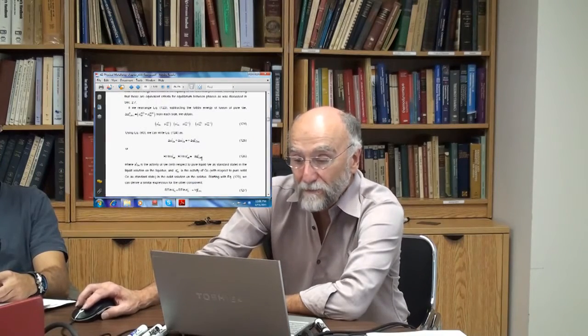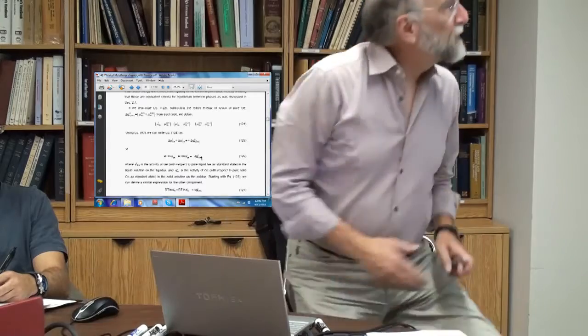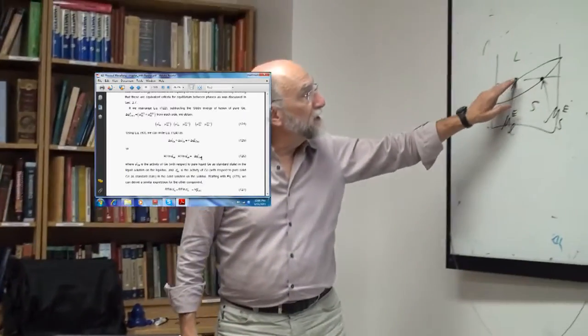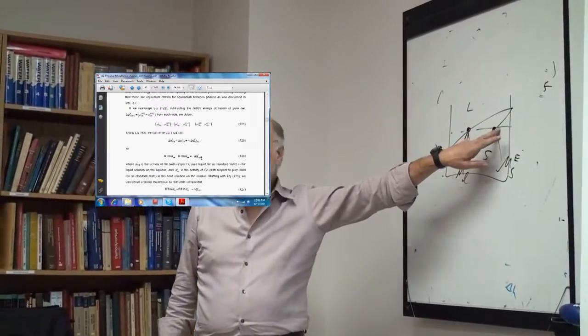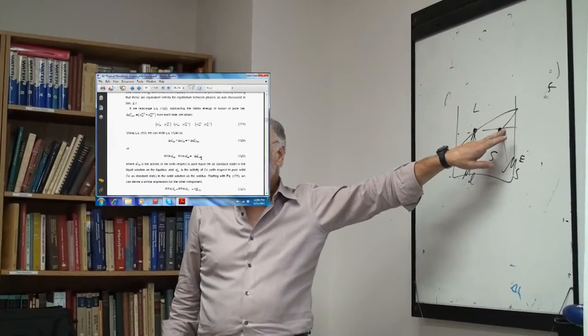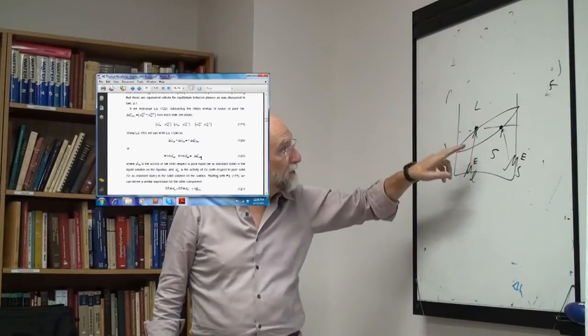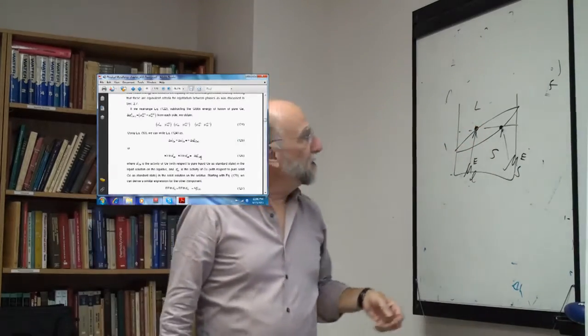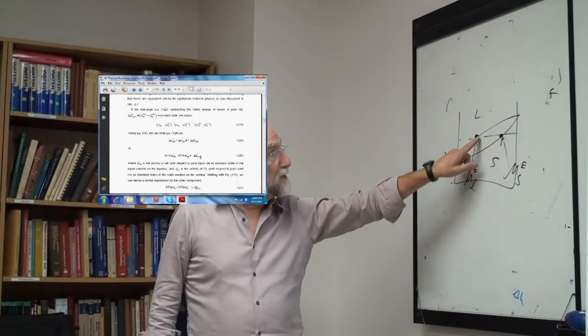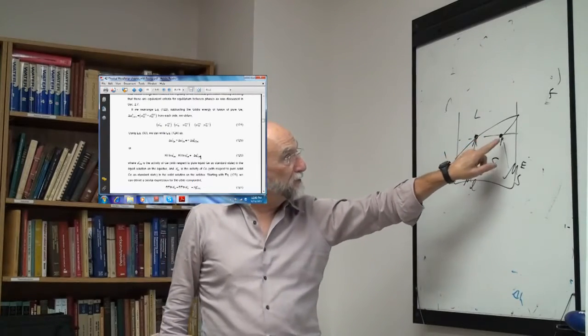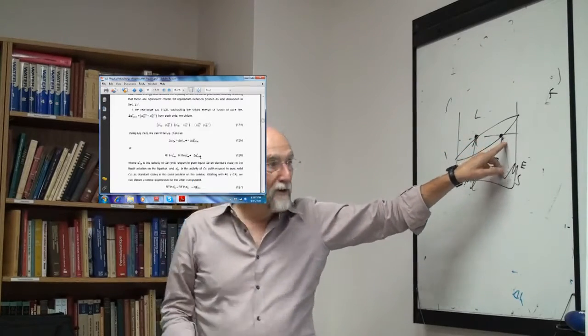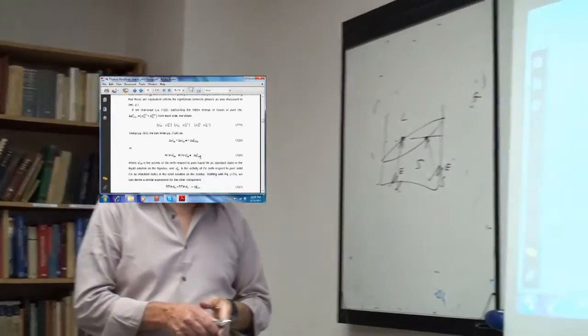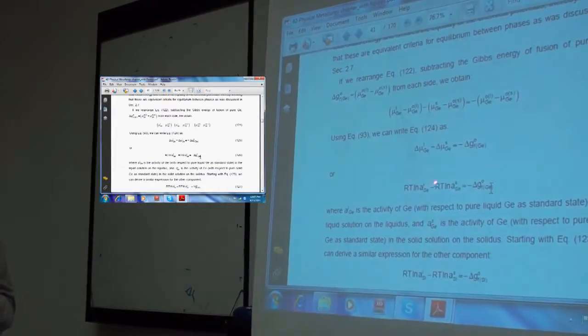Okay, now, at some temperature, at this temperature here, which is not the melting point of germanium, delta G of fusion of germanium is not zero, obviously. It's positive, but no, it's negative at that point. Okay, so I thought that I said that when two phases are in equilibrium, they have the same activity. So the activity of germanium in the liquid on the liquidus should be equal to the activity of germanium on the solidus. But, therefore, the left-hand side is zero. But it's not zero.